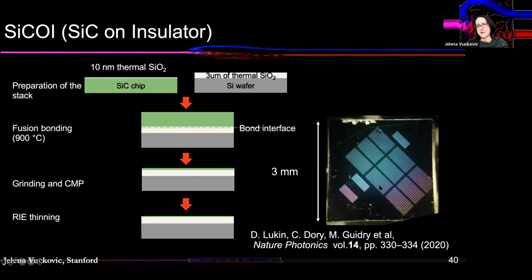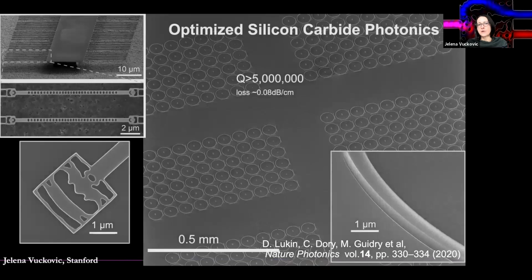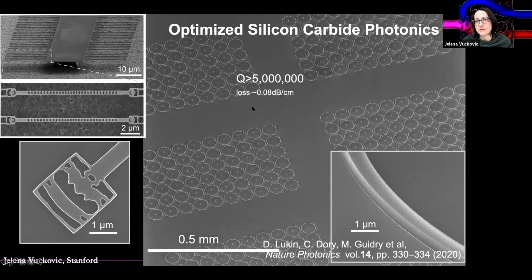And here are the chips of silicon carbide on insulator, where we can make photonics. At the moment, we're actually able to make very high quality photonics. These Q factors that we have at the moment are greater than 5 million. That's more than what we can actually see even in silicon when we do fabrication at Stanford. And loss is 0.08 dB per centimeter, which is comparable to foundry-based silicon nitride. And also we can combine this with inverse design photonics.